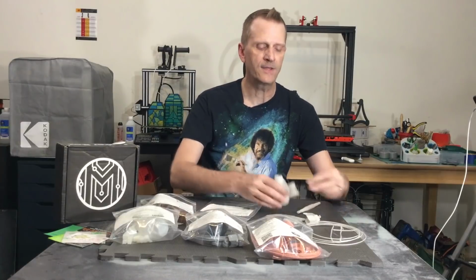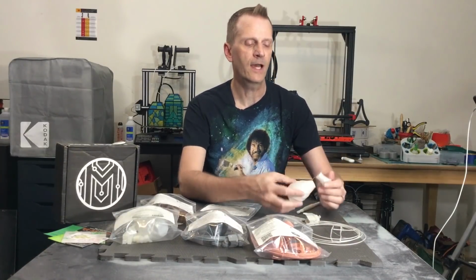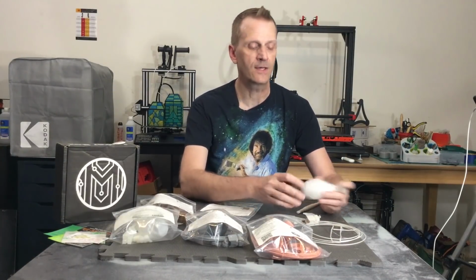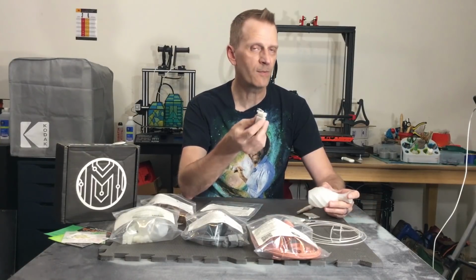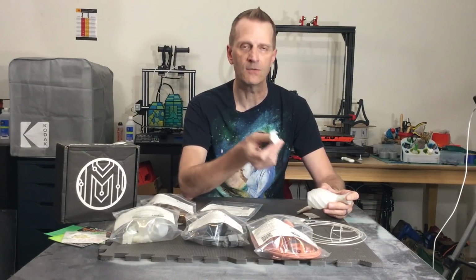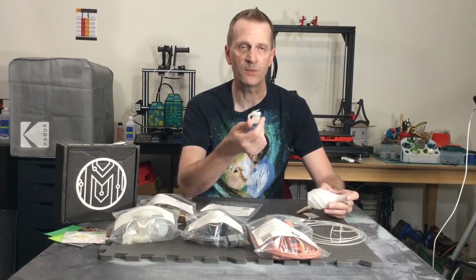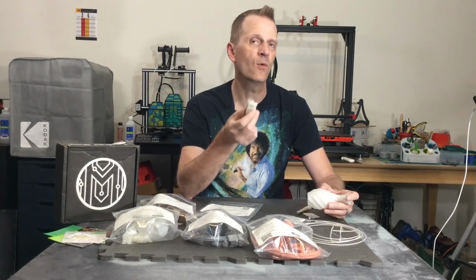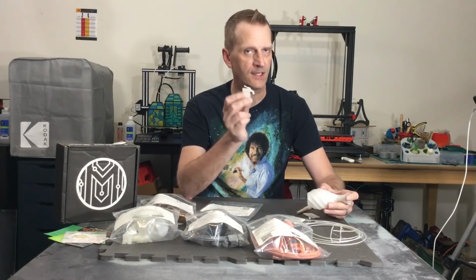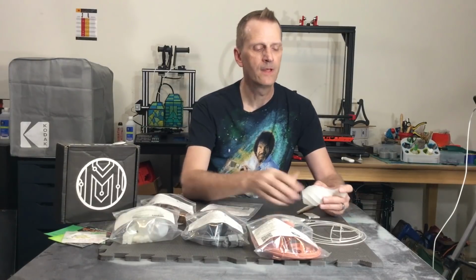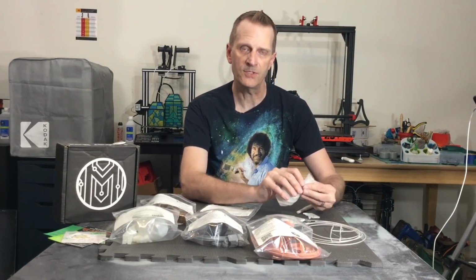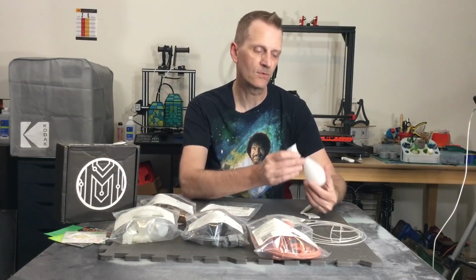So I printed out the, as you can see here, it's already broken. I printed out the Rose Twist Vase next because, in my opinion, the rest of the model had printed out well, and as you can see, seems to be pretty strong. There seems to be pretty good layer bonding, but it bonded so well to the acrylic that I broke the model taking it off. That was my thought. I printed this out at the same temperature, 235 degrees. This is the Rose Twist Vase.